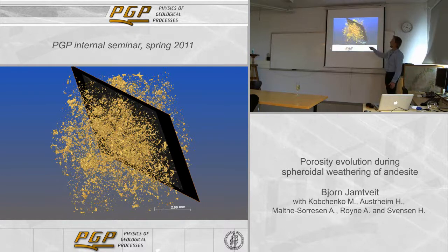It looks like a lot of pores here, but that's also because this is three-dimensional, and when you see things in 3 dimensions, you look through the system, and it looks like much more than it actually is. So it's less than 1% porosity in this picture. I couldn't really believe that it was so small, so I asked Maya to calculate this over and over again, and she keeps insisting that it's right. So that means only a small percent, maybe less than 20, maybe down to 10% of the porosity is so big that we actually see it on the CT scans.